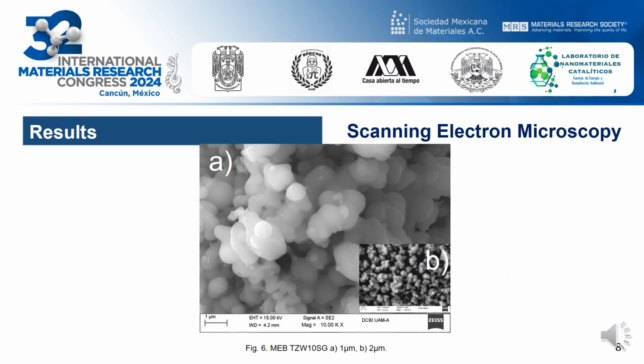SEM analysis demonstrates that the sample synthesized by sol-gel and annealed at 800 degrees shows an average particle diameter greater than the one synthesized by sonochemistry. For example, titanium zirconium tungsten with 5% by sol-gel was 2099 nanometers, against titanium zirconium tungsten with 5% by sonochemistry at 161 nanometers. As expected, the samples obtained by sonochemistry show less agglomeration than those obtained via sol-gel.